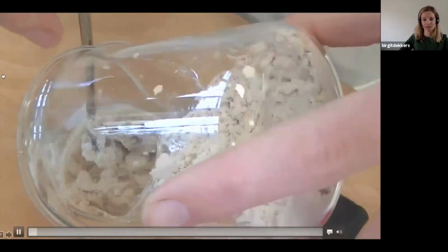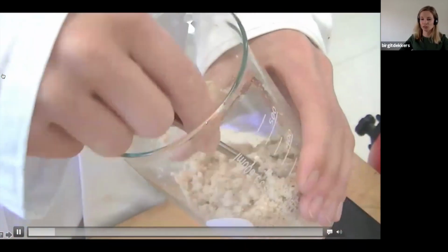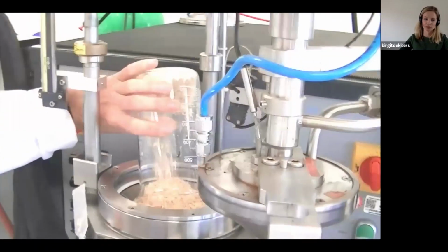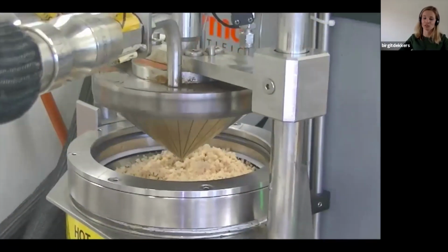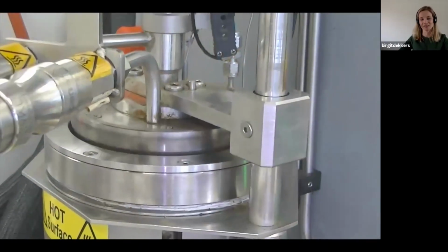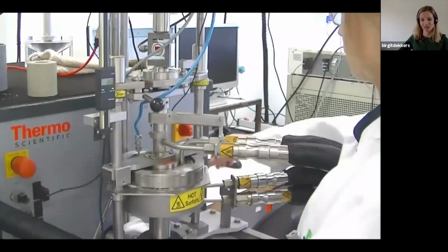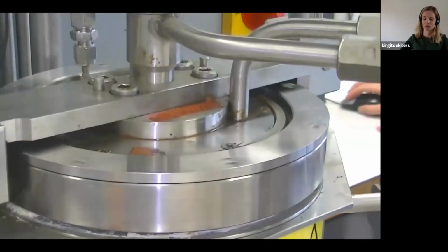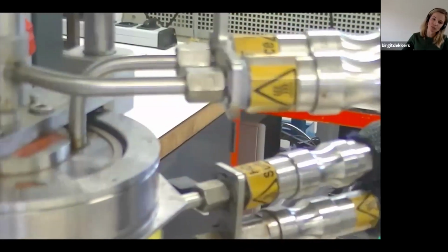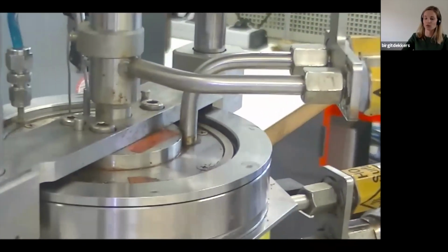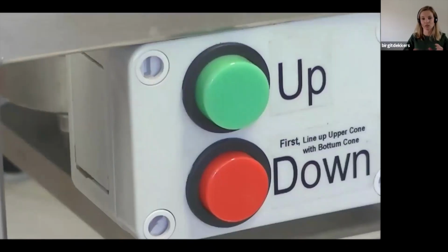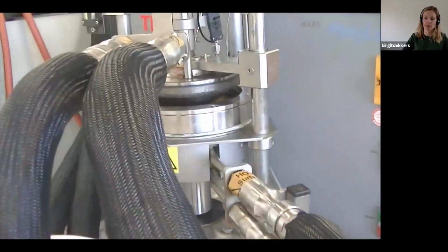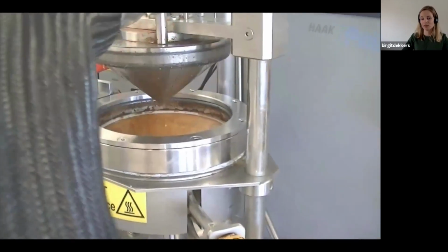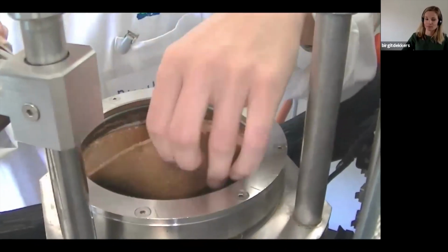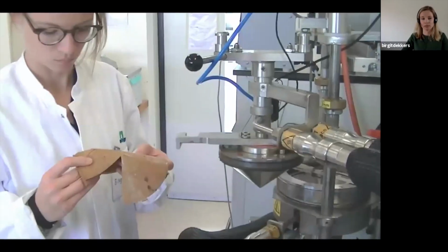In this case, I blend some plant proteins with water, and you obtain a dry dough-like mixture. This is actually what a shear cell in practice looks like. So two cones. The whole system in this case is already preheated, and the bottom cone starts rotating, the top cone remains stationary, and that's what the shear process looks like. Then upon cooling, you can open the whole system again and take out a sample.